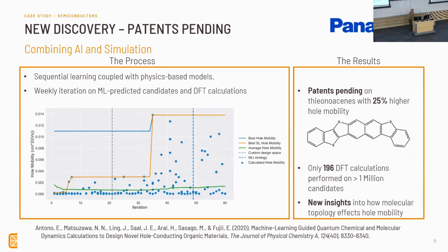The plot on the left shows off basically this sequential learning process of the iteration number at the bottom there, and on the left the metric is just the hole mobility itself. And so the higher the better for hole mobilities. And what you're basically seeing are a bunch of lines that describe the performance of our sequential learning process and our ability to hit these marks over the course of these iterations. And so the blue line corresponds to the best hole mobility period that we have available to us at the time. So our training data had one that was pretty high. That's why it starts so flat, because we weren't able to find anything better than it until like halfway through this process.